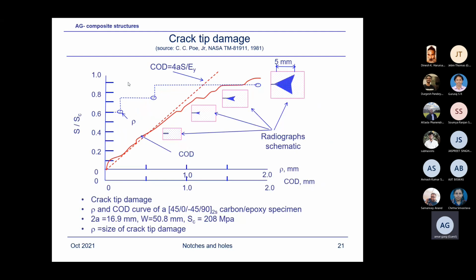Similarly, for the crack, I have tried to show similar pictures over here. I have taken this from the work of C.C. Poe, Christopher Poe from NASA. So what you are seeing here is a load displacement curve, and essentially this is showing just qualitatively the damages which are growing like this when you have a crack. So similar to the hole edge, the damage will keep on growing.